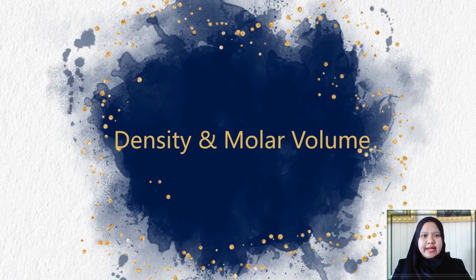According to Doweidar and Saddeek 2009, the density is a powerful tool capable of exploring the change in the structure of glass and is affected by the structural softening or compactness. This statement was supported by Siddiq et al. 2013 and Hasni Mulyati et al. 2017. Reported by Azuraida et al. 2015, molar volume can be used as a parameter to identify an open structure, which suggests that a higher value of molar volume corresponds to the maximum open structure.